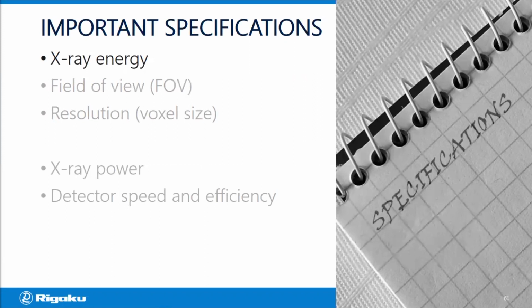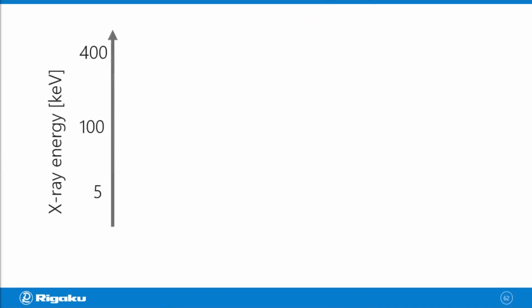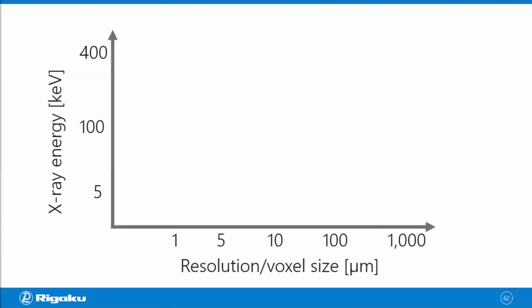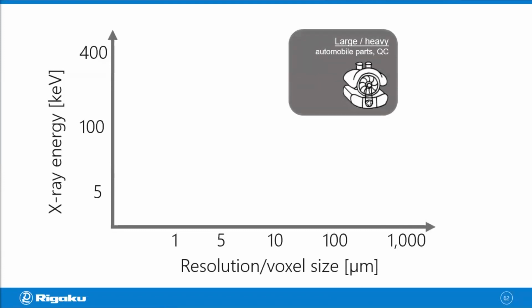First, the X-ray energy. You can roughly categorize X-ray CT scanners in three groups. And those three groups have different X-ray energy they cover. So if you put the Y-axis as your X-ray energy, then you put the X-axis as a resolution, one category would be positioned here. So if you want to see large and heavy samples, like engine parts, then you would need high energy somewhere from 200 to 450 keV. But because you're looking at a large sample, you probably don't need high resolution. So this category covers high energy, not so high resolution voxel size range.